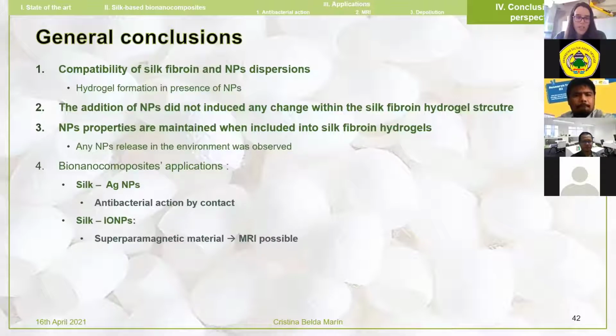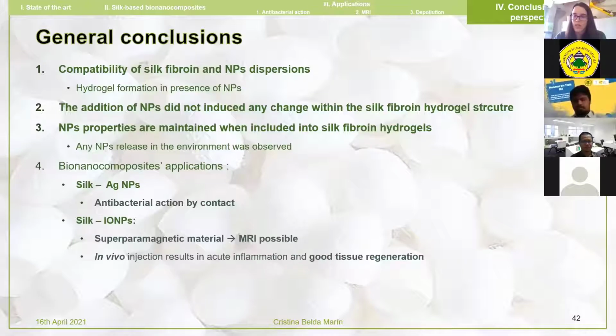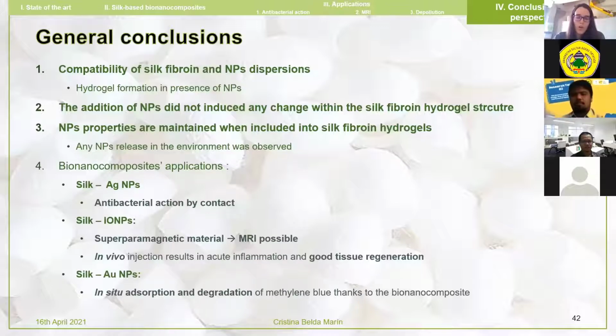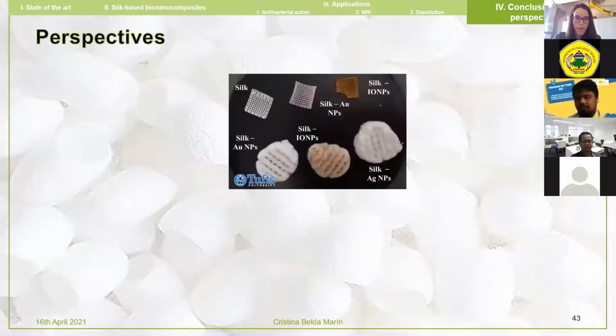For iron oxide, I have not shown, but it's possible to do magnetic resonance imaging with it. And then for silver and gold nanoparticles, we have combined the action of the silk materials, which are going to absorb, and the degradation through catalysis for organic molecules.